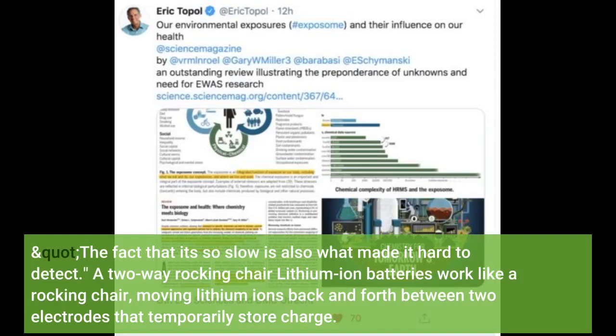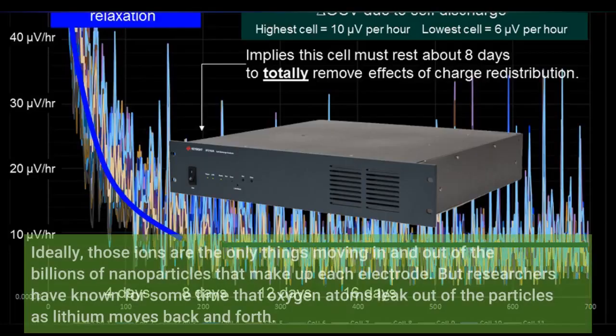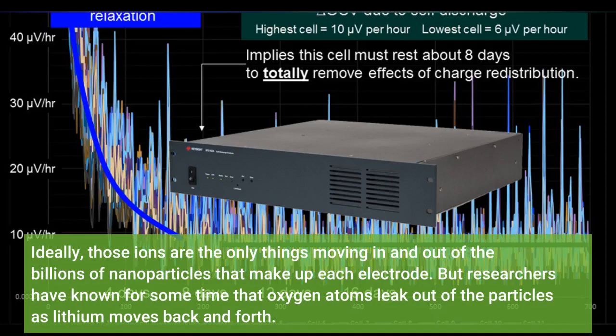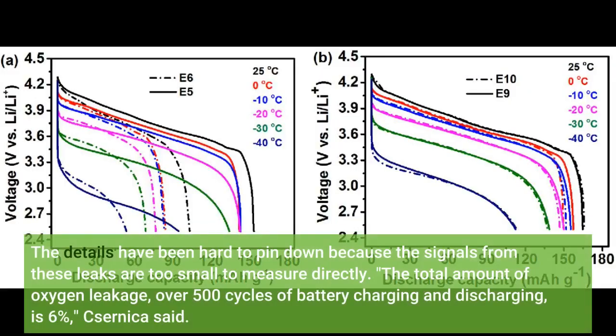A two-way rocking chair: lithium-ion batteries work like a rocking chair, moving lithium ions back and forth between two electrodes that temporarily store charge. Ideally, those ions are the only things moving in and out of the billions of nanoparticles that make up each electrode. But researchers have known for some time that oxygen atoms leak out of the particles as lithium moves back and forth. The details have been hard to pin down because the signals from these leaks are too small to measure directly. "The total amount of oxygen leakage, over 500 cycles of battery charging and discharging, is 6%," Csernica said.